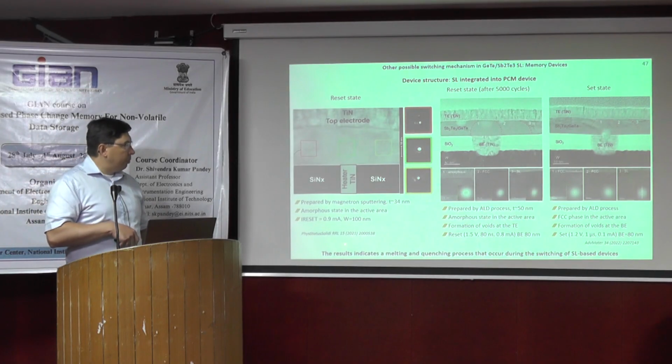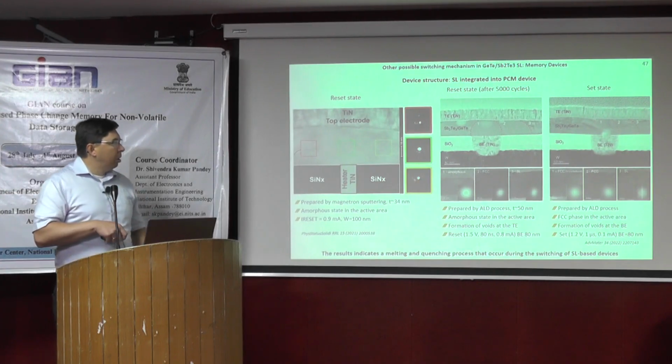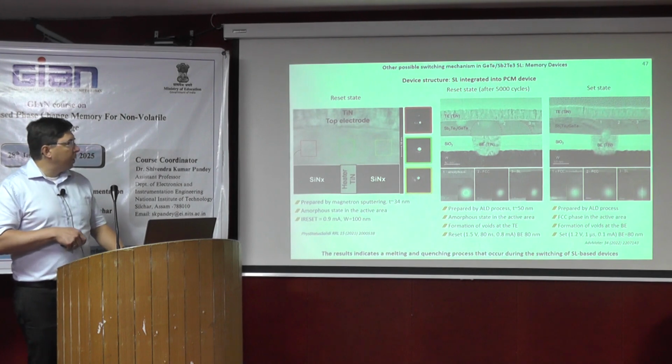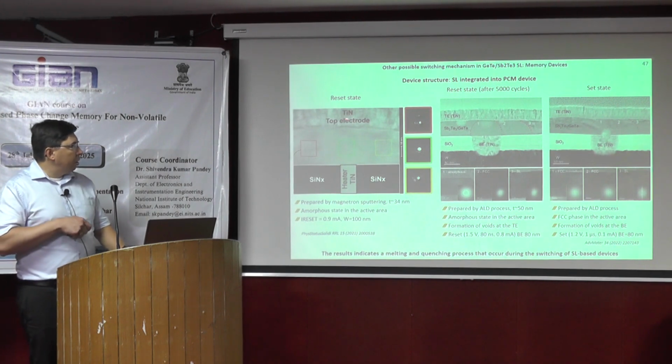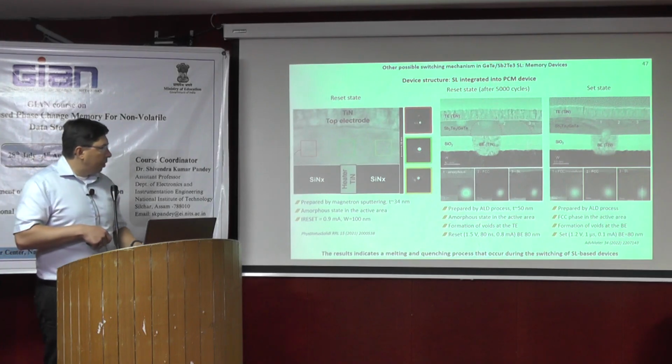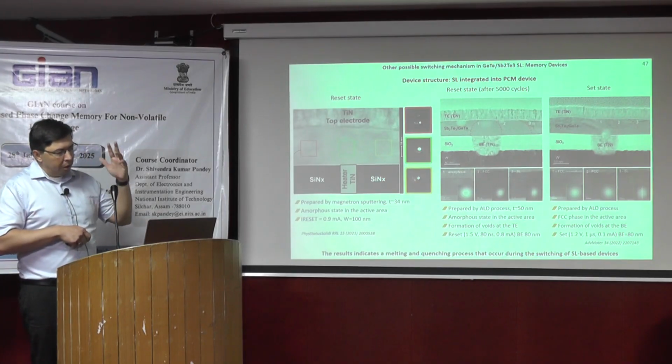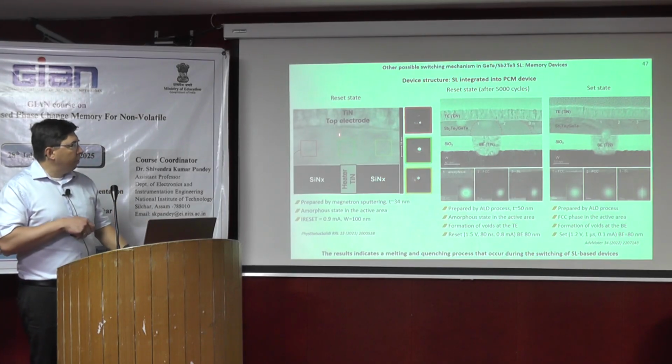One was published in 2021, then 2022. There are also several other publications, and all these publications show that if they apply a reset pulse to the superlattice system, to the highly crystalline system, they always observe a transition from the crystalline to the amorphous phase.